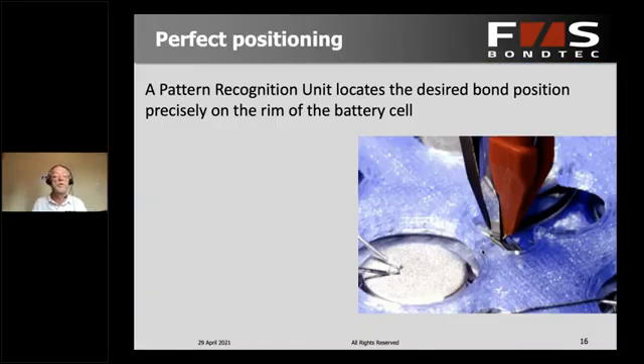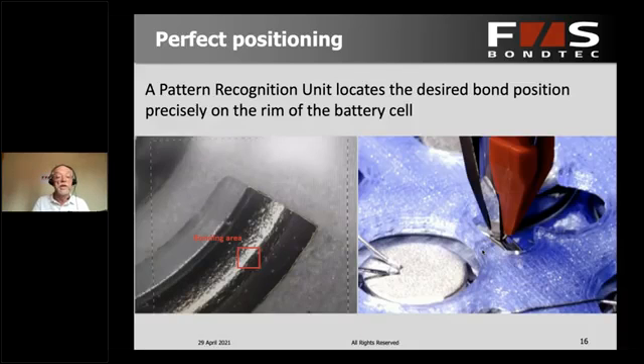But we can get around this problem because we have a pattern recognition unit in the bonder that allows us to locate the bond position very, very sharply and very precisely on the rim of the battery cell. In fact, if you look here on the left, you see the camera image from the bonder itself that shows us just what we are doing and where the bond itself is being located.